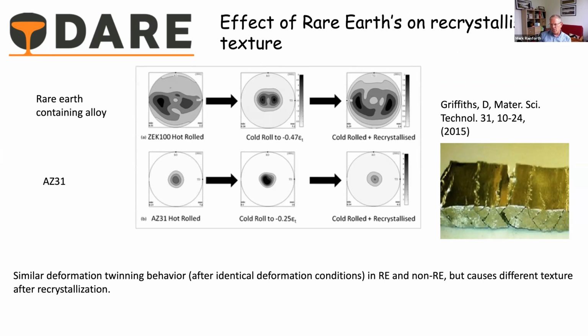And the consequence of that is when you form these alloys, you can see what you get in the right-hand image, where you get extensive cracking. So we've known for a long time that if we put rare earth elements in, we distribute this texture, it becomes much weaker, and as I say, the crystallographic texture is distributed over a much wider range.